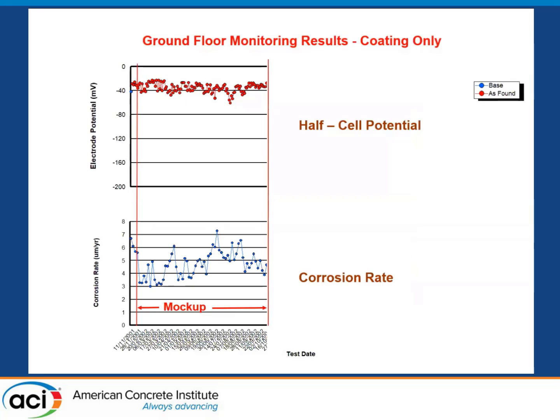And as I indicated, they then monitored this for a year, which I thought was very interesting. I haven't seen that done often, but it was a really good approach, I thought. They did the mock-ups in November of 2001. They monitored them for a year. The probes were monitored remotely, so they could gather data continuously throughout that 1 year period. And this is an example here. This is where the coating was used.